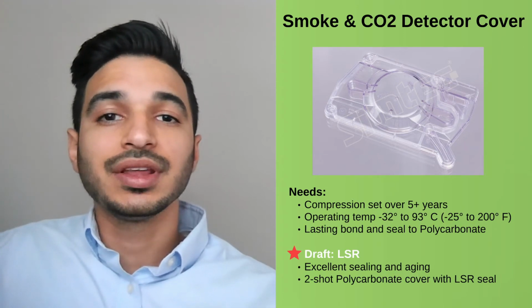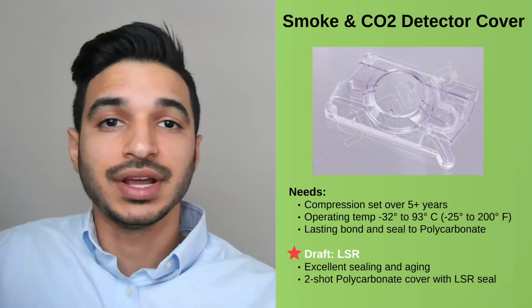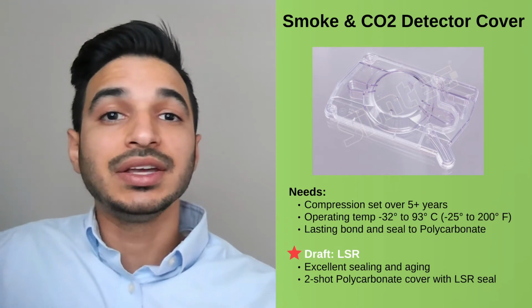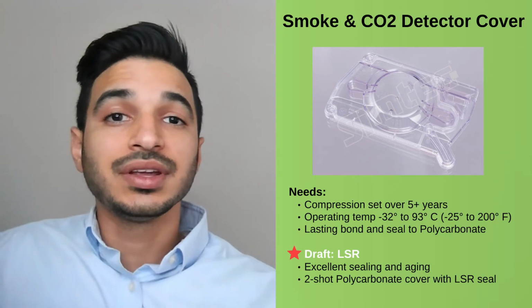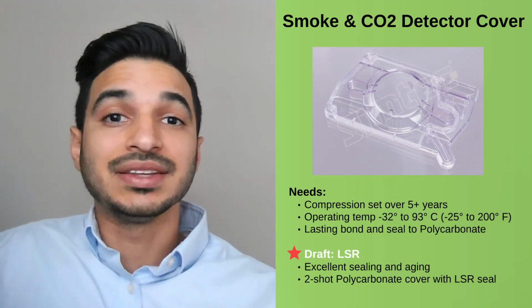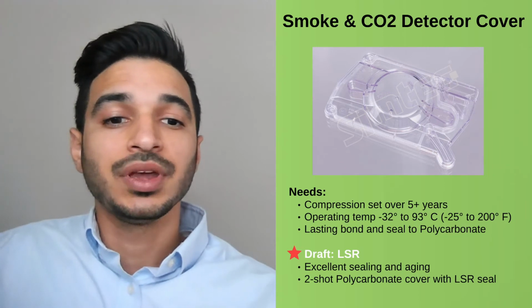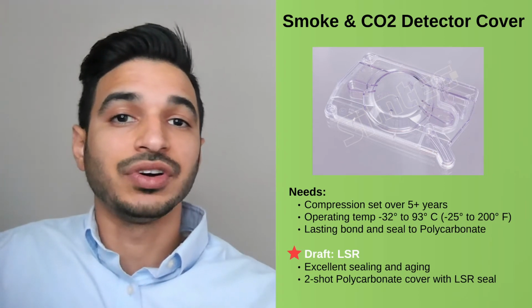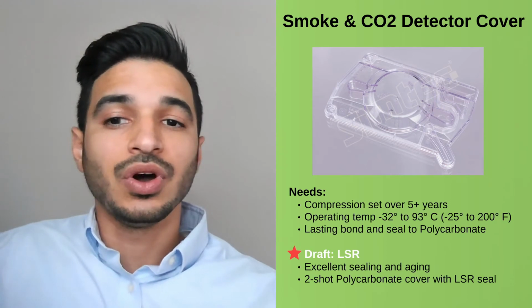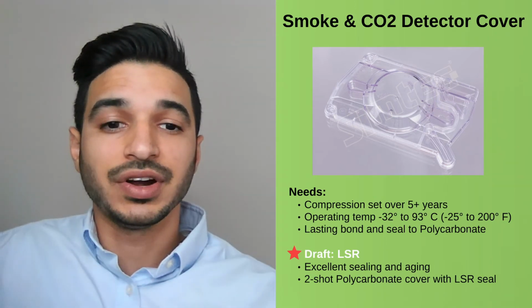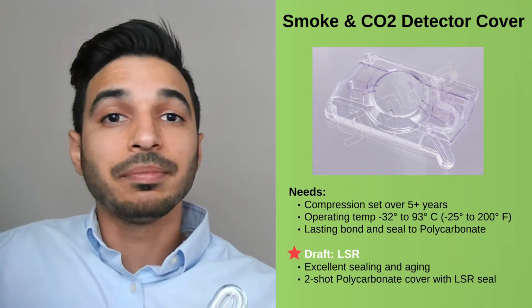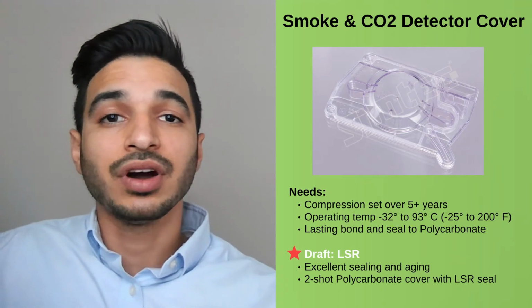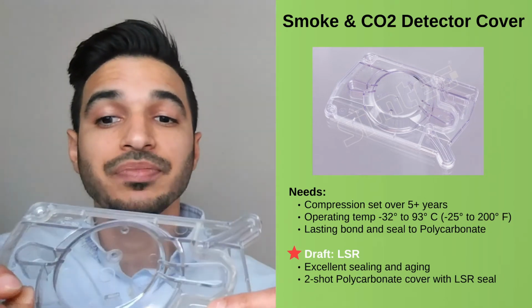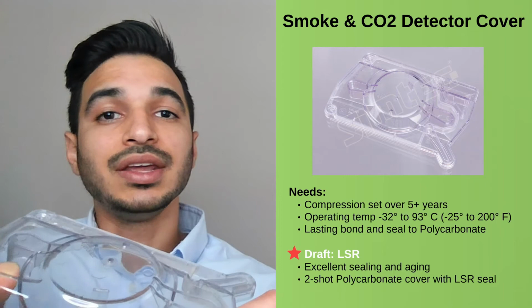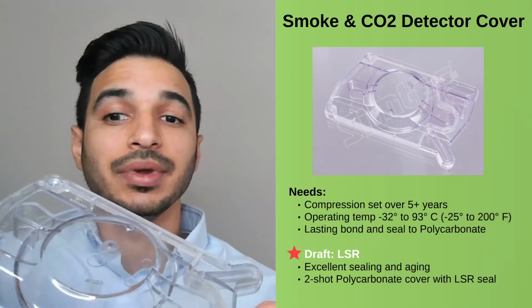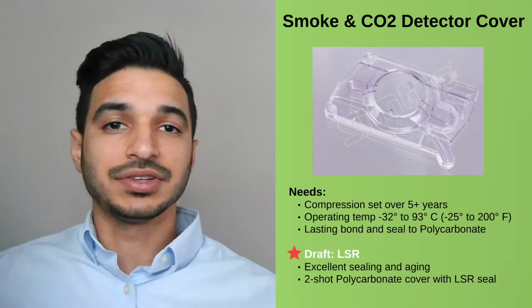But for the elastomer, we needed the compression set to be at least under 30% and withstand durations of at least 5 years or more. We wanted it to be stable and maintain its mechanical and chemical stability over the temperature ranges of -32 to 93 degrees Celsius or -25 to 200 degrees Fahrenheit. And lastly, we wanted to bond the polycarbonate. Specifically, the polycarbonate needed to be very transparent, and it needed to withstand any UV yellowing reactions that could happen over the lifetime. So we need to have UV stabilizers.